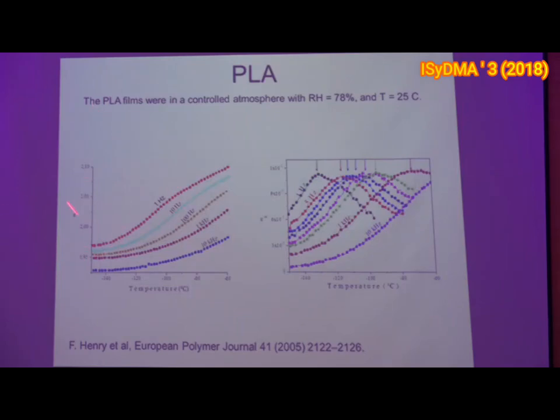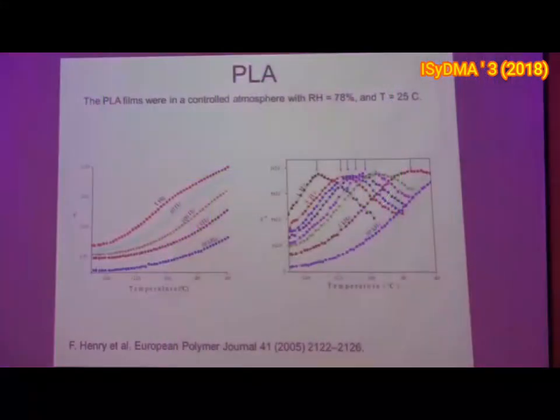So this is epsilon prime, this is epsilon double prime, that is the imaginary part, and we see here very clear peaks, and these peaks are a sign of a relaxation process. So we see that when the frequency increases, the peaks go to the right. Okay, so this is very low frequency, this is high frequency, and I can calculate exactly where these peaks are, and then I can see for each temperature where the peak is, that is, the relaxation frequency.